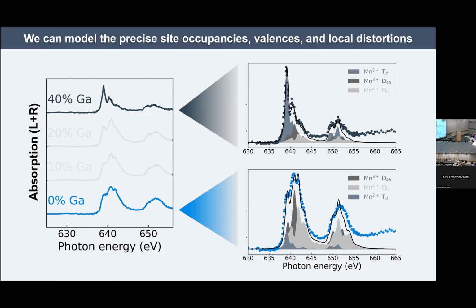And to come back to what Song said earlier about having 10 elements, and I had said there's 11, it's because not only do we have manganese 2+ and 3+, we actually find out that we have manganese 4+, which was an unexpected surprise. And what's remarkable is that in the 0% sample, those 3 manganese states, 2+, 3+, and 4+, are all in a decent proportion. There's quite a bit of each of them, enough that we cannot adequately describe the absorption spectra without accounting for each of them.